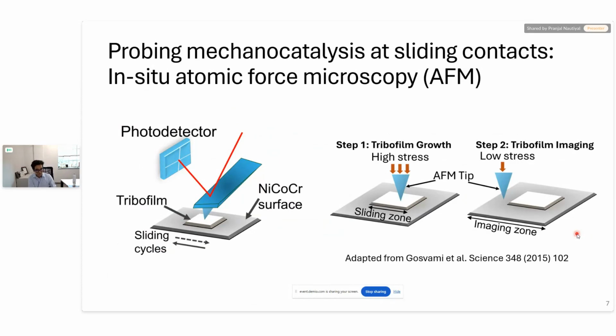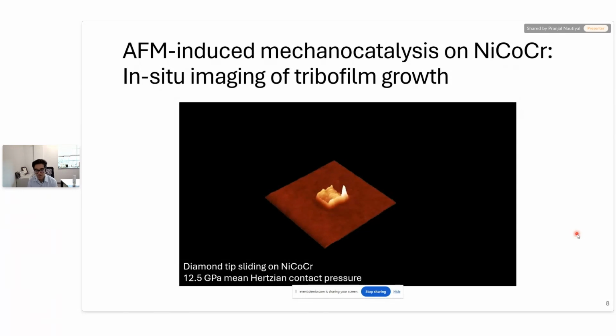So using this method, we conducted some tests on nickel, cobalt, chrome alloy at a very high 12.5 gigapascal mean Hertzian contact pressure. And as you can see in this in-situ video, as the sample was subjected to contact cycles in the central 1 by 1 micrometer square patch, we saw the formation of a thin film. I should mention that we are doing this experiment in air. So essentially, we are relying on ambient hydrocarbons to induce these mechanochemical tribofilm formation. And clearly, nickel, cobalt, chrome is catalyzing the formation of these films. These stresses are pretty high. They're very high. These stresses usually induce significant wear and deformation of alloys. But in this case, because of this mechanochemical film formation, the wear of the alloy is mitigated.